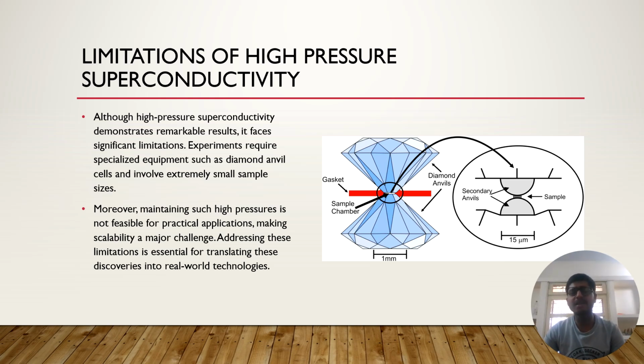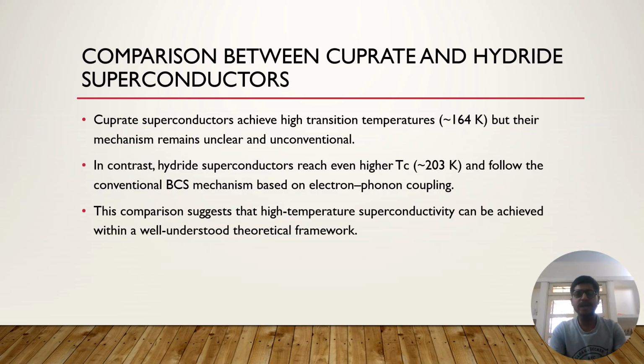To understand its importance, let us compare it with other superconductors. Cuprate superconductors were the first materials to achieve high transition temperatures, reaching values around 164 Kelvin. However, their mechanism is still not fully understood and is often described as unconventional, involving strong electron correlations rather than simple electron-phonon interaction. In contrast, hydride superconductors follow the conventional BCS mechanism, where superconductivity arises due to electron-phonon coupling. Despite this, hydrides achieve even higher transition temperatures exceeding 200 Kelvin.